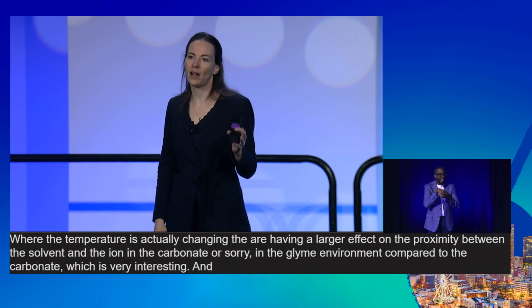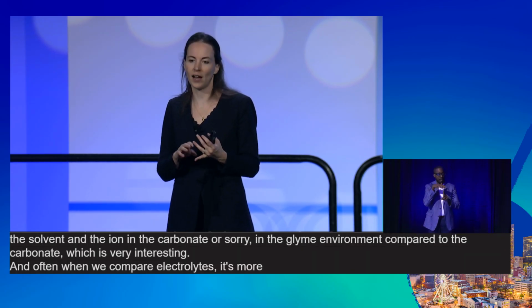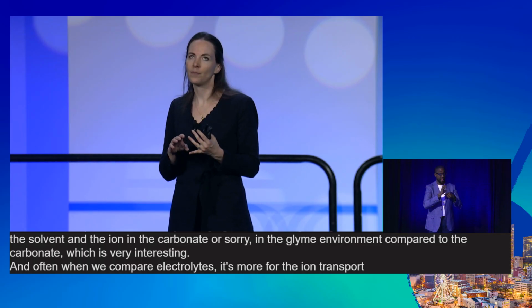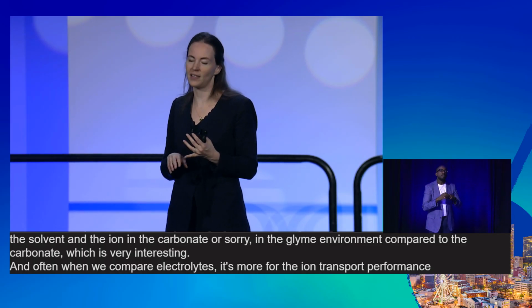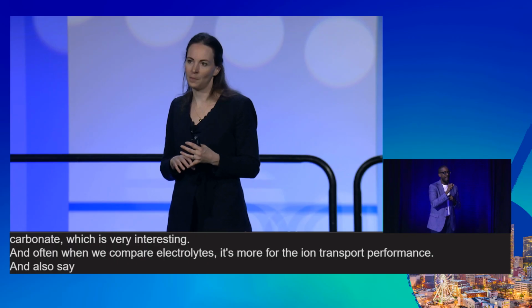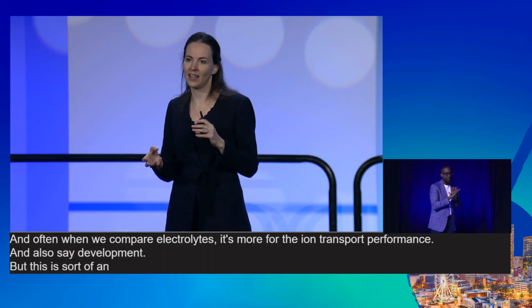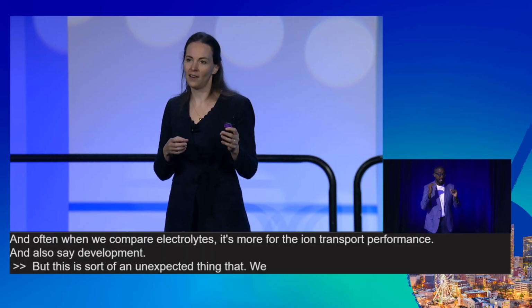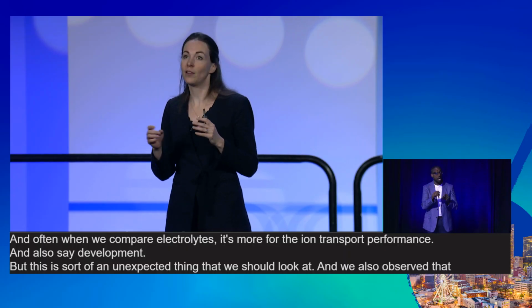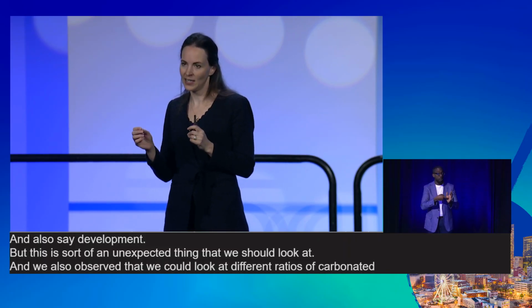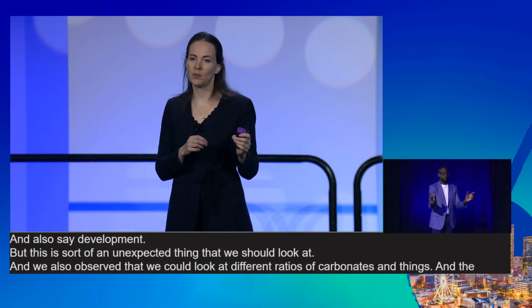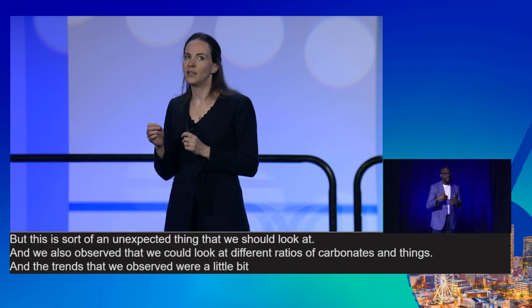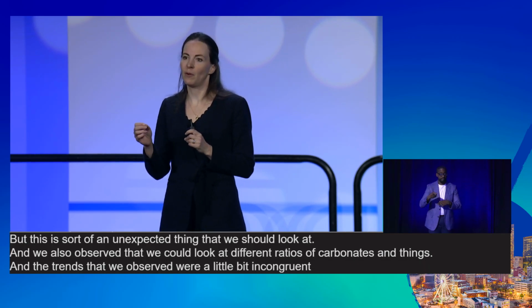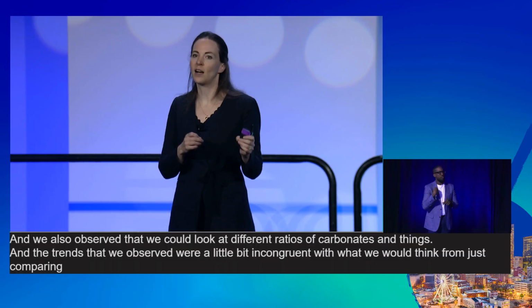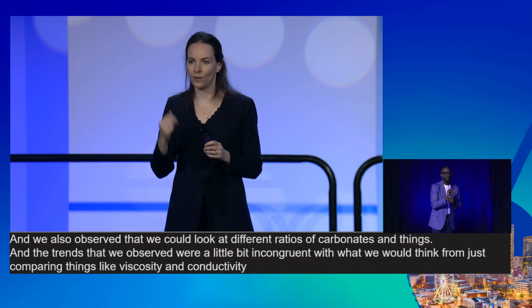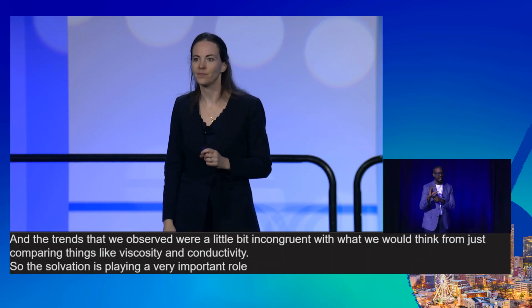And often when we compare electrolytes, it's more for the ion transport performance and also SEI development. But this is sort of an unexpected thing that we should look at. And we also observed that we could look at different ratios of carbonates and things. And the trends that we observed were a little bit incongruent with what we would think from just comparing things like viscosity and conductivity. So the solvation is playing a very important role.